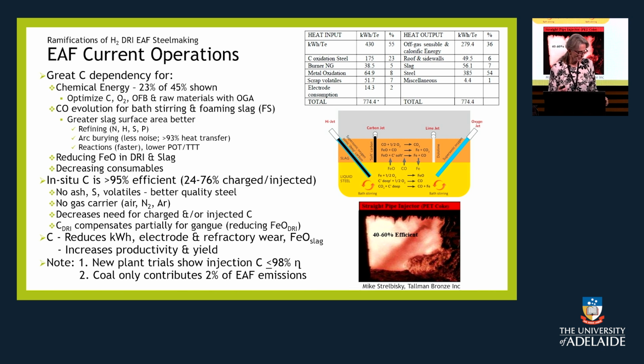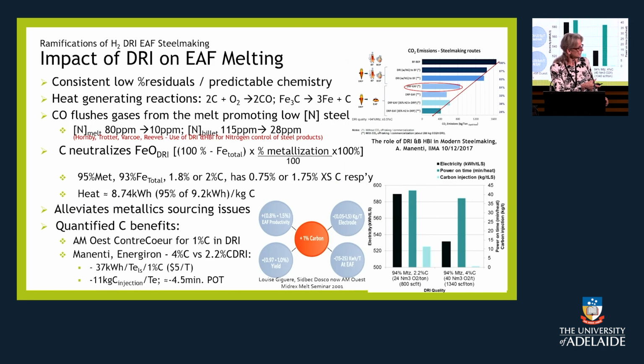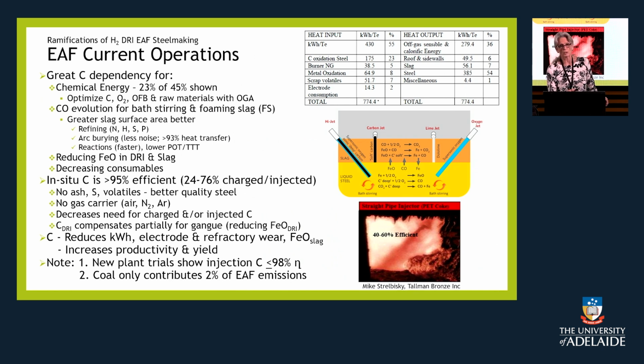It's also being added using carrier gases, and you also have all of the sulfur and the bad entities in the carbons. So carbon's basically reducing the kilowatt hours, the electrodes and refractory wear. It reduces the FeO in the slag, which is a big concern because that's the biggest contributor to the cost of steelmaking, basically. Now there's new plant injection trials shown on the bottom, and I'll go through this a little bit more later. But they found a way of making the injection carbon 98% efficient. And just as an FYI, the coal only contributes about 2% of the EAF emissions.